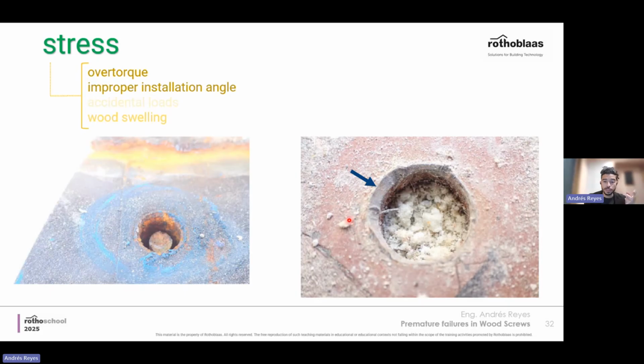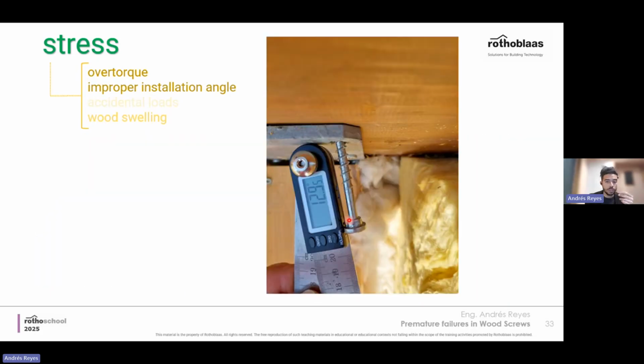And here it could be a mix of improper installation angle and over torque. You see here, this is another construction site. You see a screw that, in this case, was inserted at 13 degrees. So these things happen. This is what they look like, and it's not even that bent. If you've been on a construction site, you know that this can happen from time to time. But this, especially combined with over torque, can lead to weakening the screw in the best case scenario, or in other cases, they can fail.